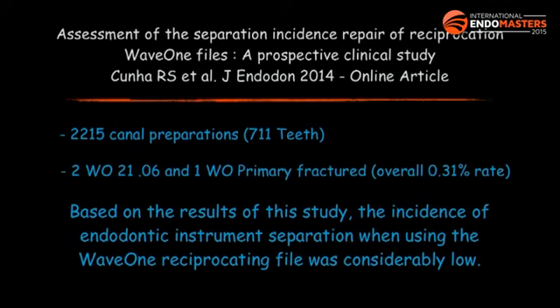Basically, that was done with Wave.One, and you had, like you can see, 2,215 canal preparations on 711 teeth. The fracture rate: basically 3 files fractured. 2 Wave.One small, the 21/06 taper, and 1 Wave.One primary, which is the 25/.08 taper. The overall fracture rate is 0.31%. If you take a look anywhere in the literature concerning continuous rotation, the fracture rate will go somewhere between 3-4% up to 8-10%.